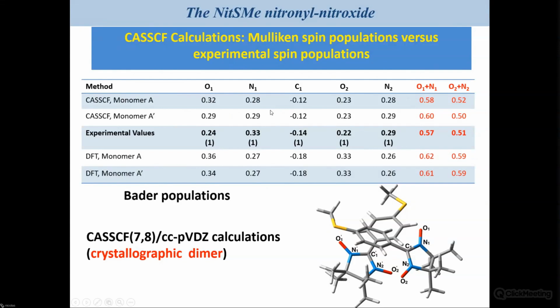And you observe here the result of the Mulliken spin population obtained from that kind of calculation compared to the experimental value. And you see that if you first look at the experimental value, you have a dissymmetry if you compare the summation of the spin density on one arm compared to the second arm. And this is something which is clearly appearing in the CASSCF calculation, but is not so clear, maybe not at all, in the DFT calculation.